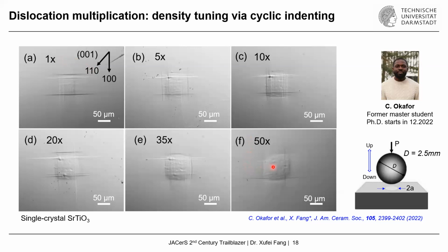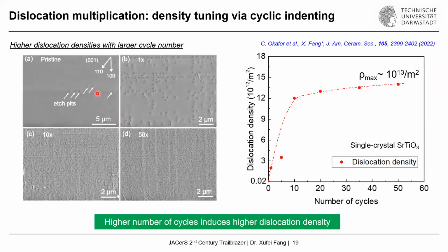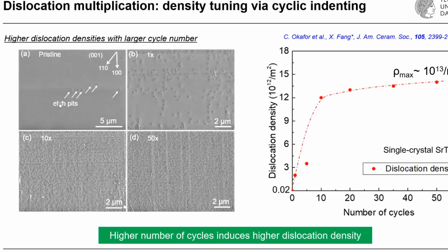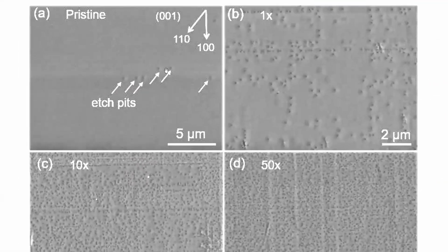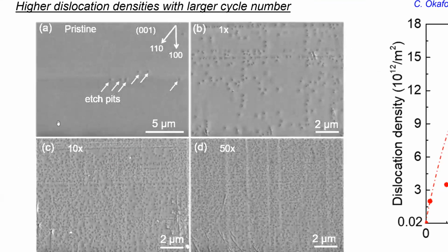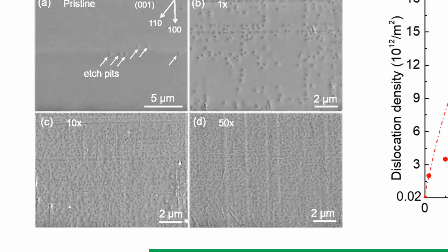As you may see, the slip traces here, all these vertical and horizontal lines, are the indication of the plastic deformation. And when we take a closer look, again using the chemical etching technique, we see that the dislocation densities are increasing. For example, here is the pristine sample where you barely see any dislocations, and after 1 cycle, we see a lot more. After 10 cycles and 50 cycles, we see many, many more. And also there seems to be a saturation of the dislocation etch pits.